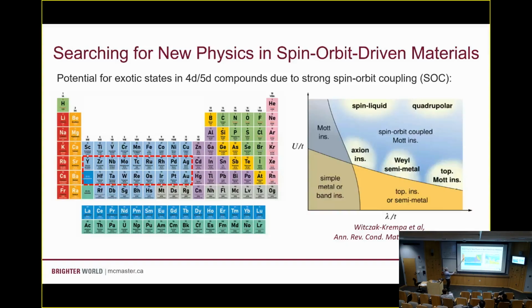Okay, so in general, as you move down the periodic table from your more common 3D transition metals, your iron, cobalt, nickel, copper magnets, as you go down here, your electronic wave functions become broader, more spatially extended. The electronic correlation effects become weaker. The spin orbit coupling, which is sort of roughly going like the atomic number, that becomes larger. And so you reach a place in these 4D and 5D transition metals where you have about 3 or 4 different energy scales that are all of about the same order of magnitude. Okay? So you get this interesting balance between correlations, crystal electric field, Hund's coupling, and spin orbit coupling.